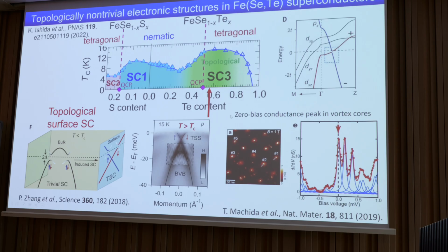And then the group by Professor Shin and Hongding have shown that around here you actually see topological surface states like this. So they suggested that in the bulk you have superconductivity, possibly S-wave, and then you can actually induce the topological superconducting state at the surface.